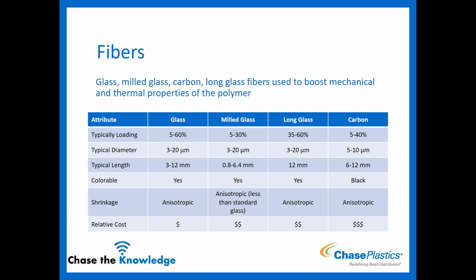So that's kind of a bridge, maybe, where you are having issues with the shrinkage because you went to standard glass and it was too much. Maybe we find use in milled glass. Then you have long glass fiber, which is going to be standard loading, 35 to 60%, much longer length. So it goes all the way up to your 12 millimeter and then beyond. And so same thing, anisotropic shrink. This is great for stuff where you need a pretty good boost in mechanical properties.